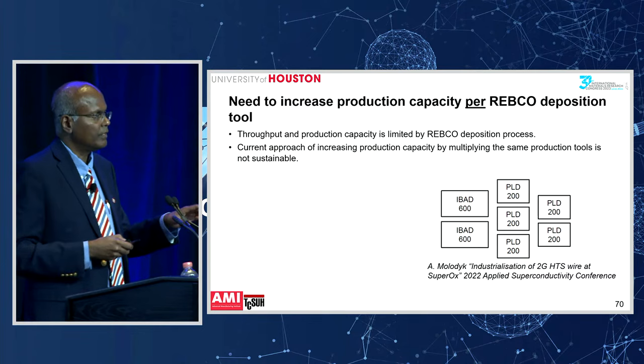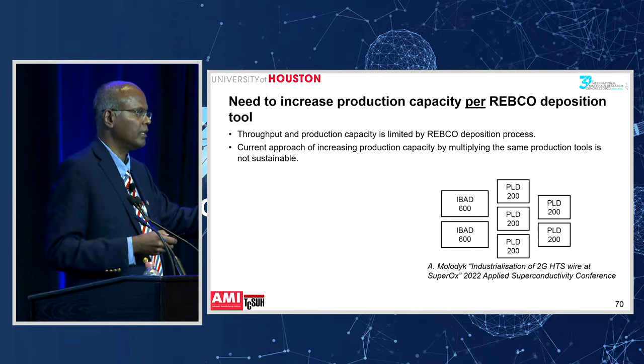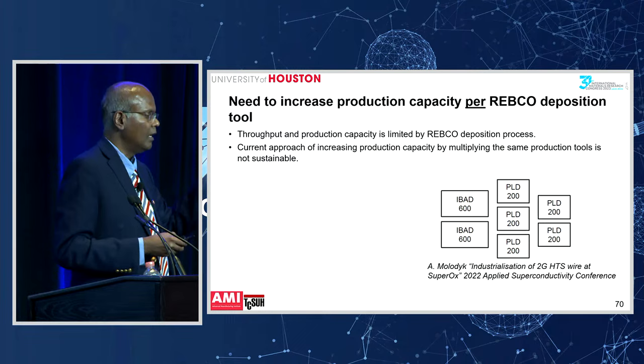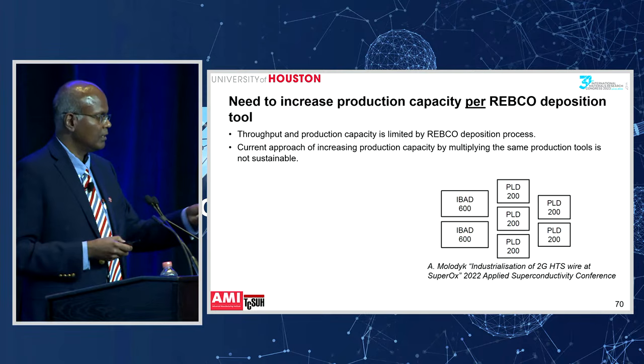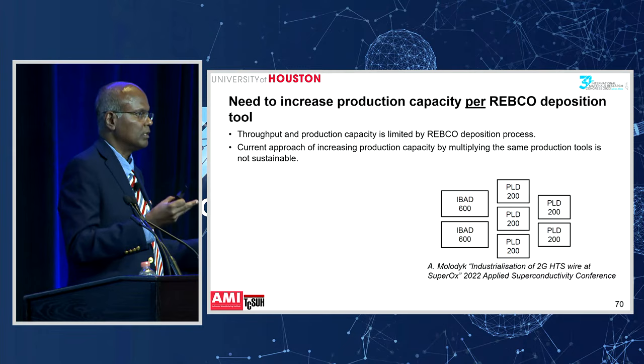Like I said, there are many different processes. You have substrate, you have the buffer layers, you have the superconductor, you have the silver, you have the copper, but the superconductor is really the rate limiting step. So what industry is doing right now, in this case PLD or pulsed laser deposition, they are just multiplying the tools, just adding 5 tools, 10 tools, just to increase the capacity, which obviously is not the optimal way to do it.